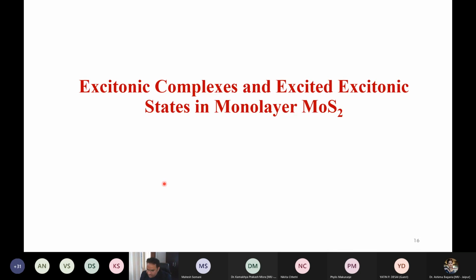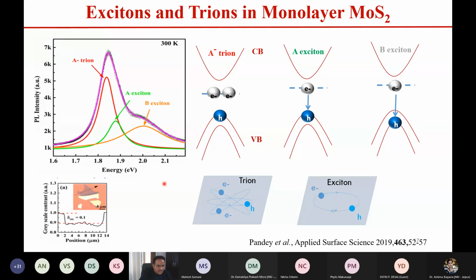So as I mentioned, the monolayer of MoS2 has a direct band gap, okay, and it shows a very strong photoluminescence. And the general understanding for these materials is that you see a lot of excitons in these materials. What you see on the screen is the monolayer of MoS2, and this is the optical contrast from where we have identified, okay, this is the monolayer. And once you have the monolayer, we have done the Raman spectroscopy to characterize, and then the PL spectroscopy. Now you look at PL spectroscopy here. So this is the PL data.